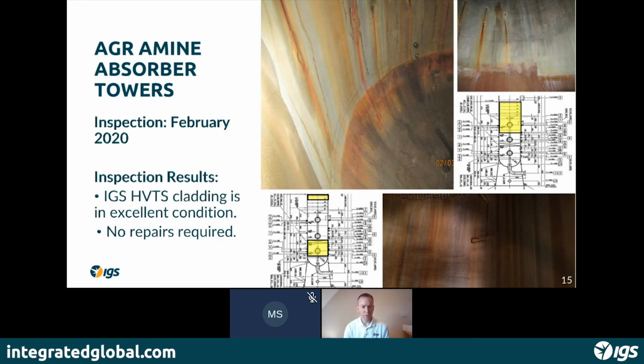internal cladding. When we do an inspection, what we can do is measure the thickness of the thermal spray cladding on top of the steel. So we have thickness maps from when we do the original application, and then we can compare those to thickness maps we make during an inspection. Typically in a corrosive environment, you don't see any reduction in the thickness. If you do have erosion taking place, obviously that's a mechanical process. And if you do remove some of the thickness, then that can be reapplied locally as required during the shutdown. So it's a system that can be repaired in situ. There's no issues with doing localized repairs if that's required after it's been in service.